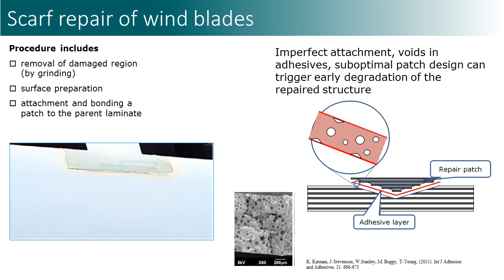Repair procedure includes removal of damaged region, surface preparation, attachment, and bonding a patch to the parent laminate. The patch can be applied as a soft or hard patch. A soft patch is co-cured together with the adhesive at the same time, while a hard patch is pre-manufactured in a mold. An imperfect attachment, voids in adhesives, and suboptimal patch design can lead to the early degradation of the repaired structure.